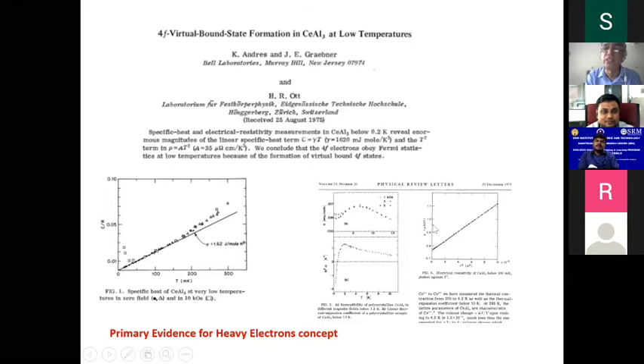Okay, and there are also other interesting anomalies here. Look at the resistivity. People in the field will know better that resistivity varies like T squared for any metallic system, ideally, called Fermi liquids. So there's a T squared coefficient, which is supposed to be extremely small, but in this case it is very huge.